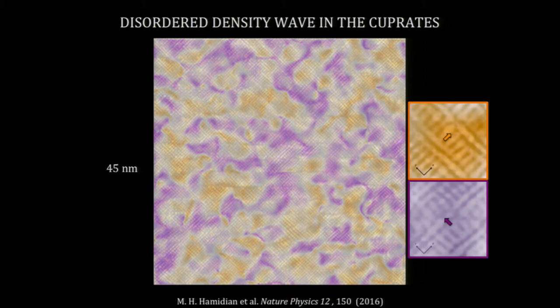Something very peculiar about this density wave is that if you were to take a crayon and color parts of the field of view in which the density wave runs in this direction, so you can see these stripes, and then color where it runs in the perpendicular direction, you get this very disordered pattern. So whatever is generating the density wave, it's not doing it as a long-range density wave. There seems to be something pinning disorder into the system. It might be intrinsic. It might be due to impurities. We don't know yet. But it is something that's rather disordered.